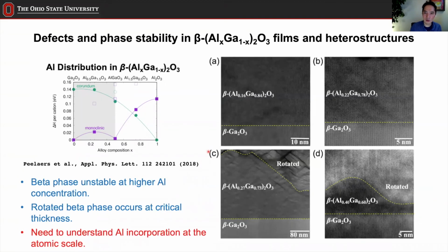Okay, so if you look at the entire film of aluminum gallium oxide, now we have looked at different aluminum concentrations. This has 16% aluminum, so it's increasing, 22% aluminum, 27%, 40%. Now, as you can see, at lower aluminum concentration, the overall structure is pretty good. But as you increase the aluminum concentration, the structure becomes a little degraded, right? So if you go to 40% aluminum, you can see the growth of beta phase only extends to about 5 to 10 nanometers, and then after that, the structure becomes defective.